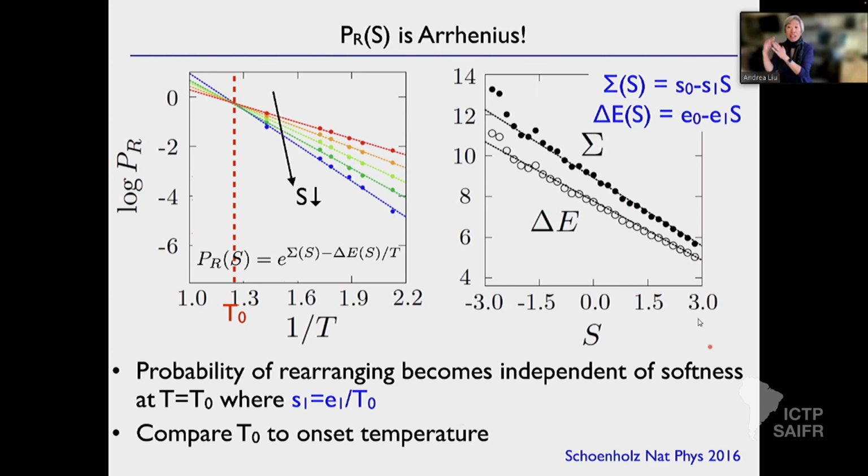So in fact, if you have a lot of defects and you now shear the system, what you see is ductile plastic behavior and avalanches, crackling noise. If you take the very well equilibrated system with few defects and very low average softness, you see shear banding and brittle failure right away. So it really does depend, and that difference you can see in the softness field.